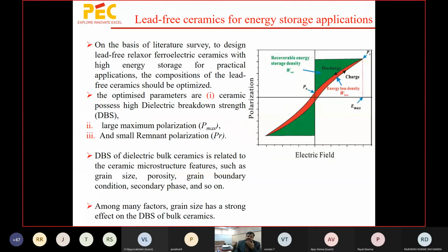In the same material, we studied energy storage applications, right? For energy storage applications, basically we need the relaxor type. As I already told you, relaxors are those materials in which the hysteresis loop is very slim as compared to a good ferroelectric. So we cannot say that these are not good ferroelectrics; they are also good ferroelectrics for different applications. In this case, the retentivity and coercivity are very low, right? The red area, the area of the loop, shows the loss, as you already know for magnetic materials. And the green shaded area is the recoverable energy storage, right?